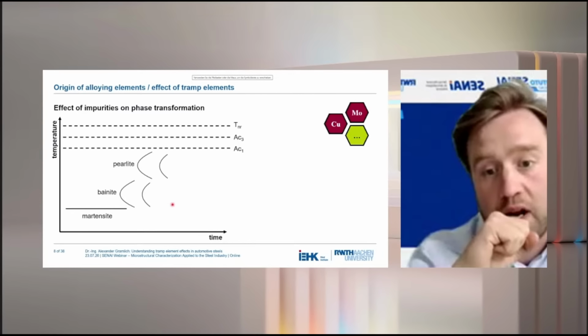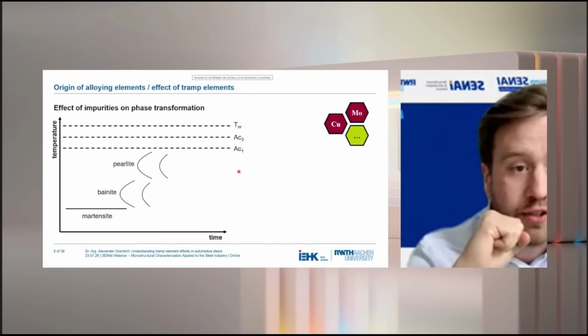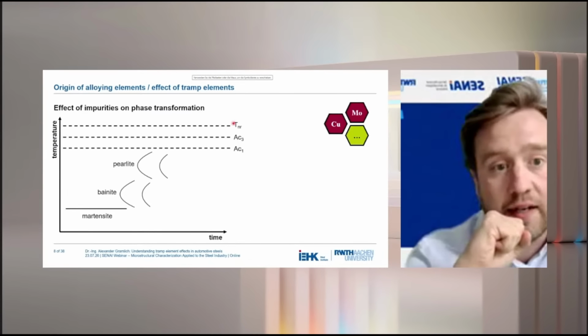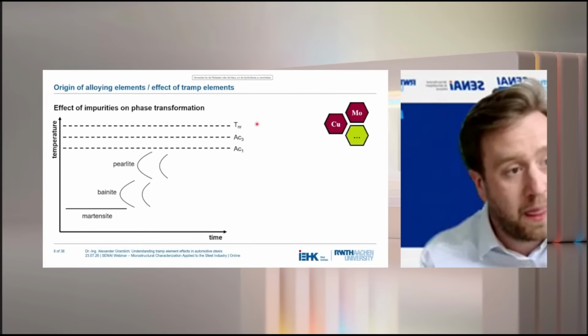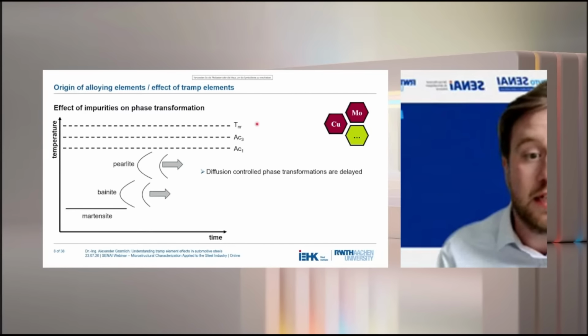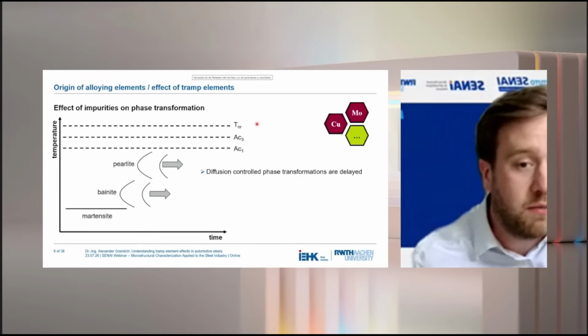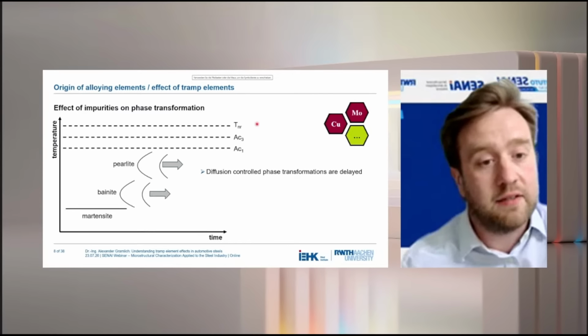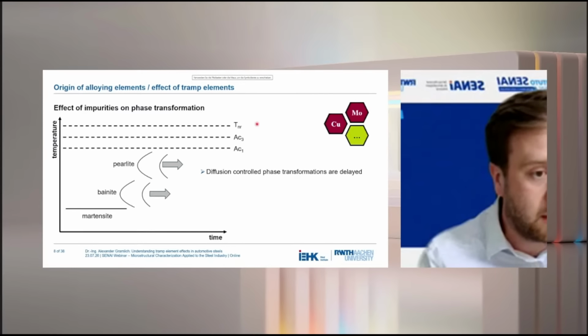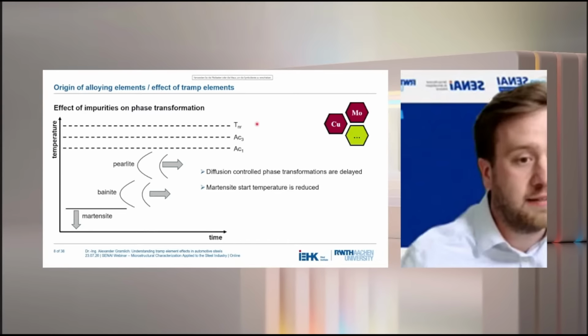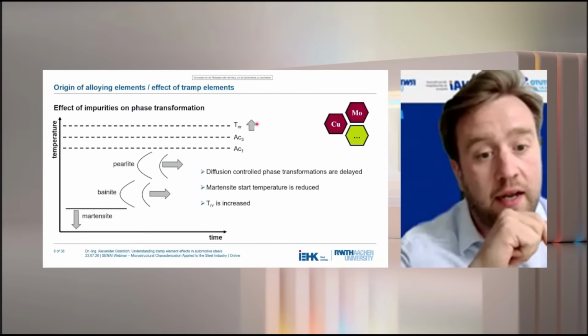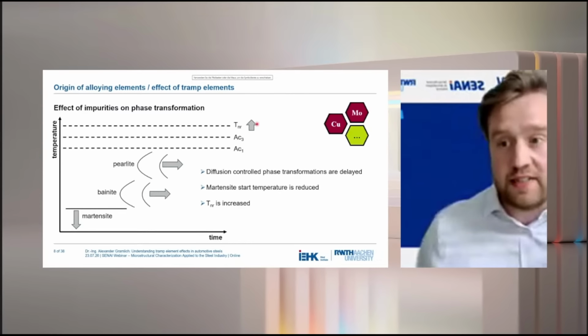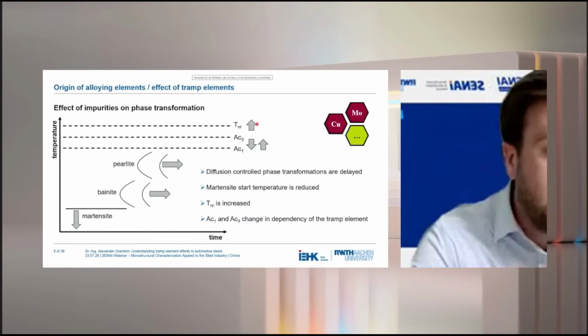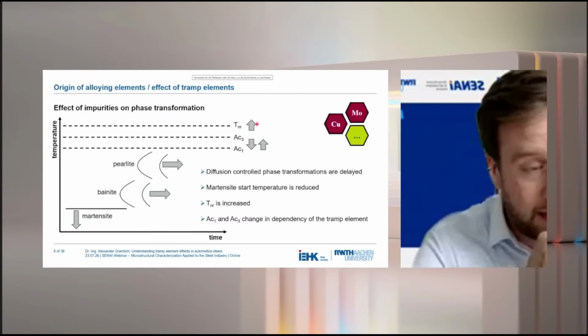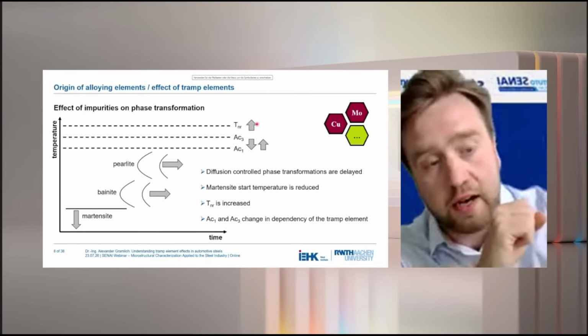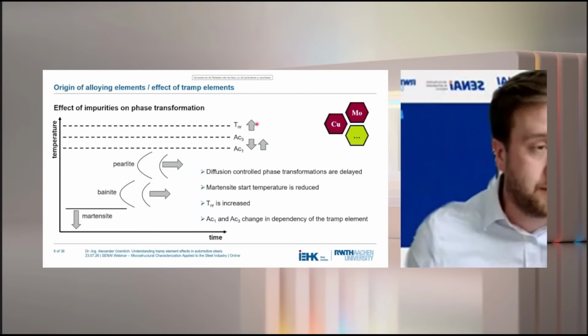We have here the pearlite and bainite forming area. We have the martensite start temperature, and we have Ac1, Ac3, and the temperature for no recrystallization. And here we are also seeing effects schematically. So for example, our tramp elements will move the pearlite and the bainite field to the right, as all of these diffusion controlled phase transformations are usually delayed. We will have, in most cases, a reduction of the martensite start temperature, and also our temperature for no recrystallization is increased. And finally, Ac1 and Ac3 change in dependency of the tramp elements. Why is this important? Because these diagrams are used to design every heat treatment process in the industry.